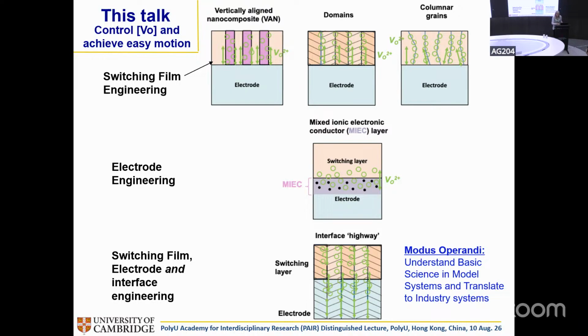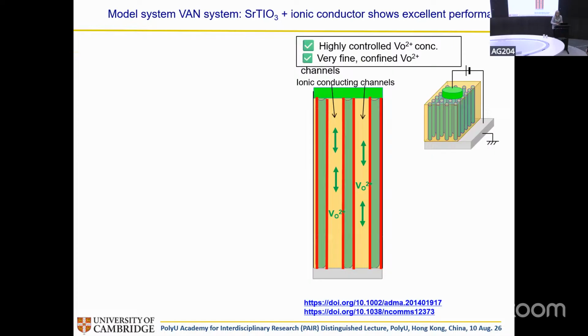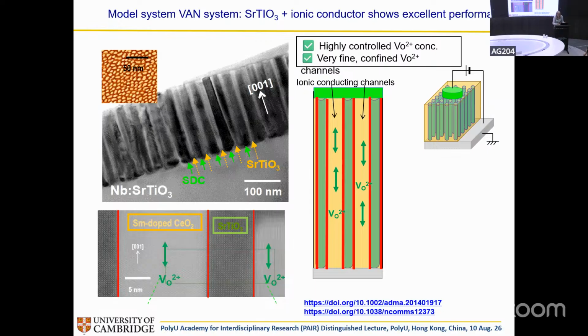Okay, so let me give you that example first. And this was some work we did around 10 years ago, with a wonderful Korean postdoc, in fact, in my group, where we said, let's look at these ionic channels. Let's create ionic channels, and let's create vertical conducting channels in this composite kind of structure here in a thin film. It's highly epitaxial. It's like a single crystal. And let's see, can we, by understanding how the oxygen moves, by making the path straight, by controlling this beautiful structure, can we get much better properties? And so, of course, I'm going to say yes, but this is what the structure looks like on the left here. We have about 20 nanometer pillars, the matrix material, and that's what it looks like on the surface, like pillars in a matrix.